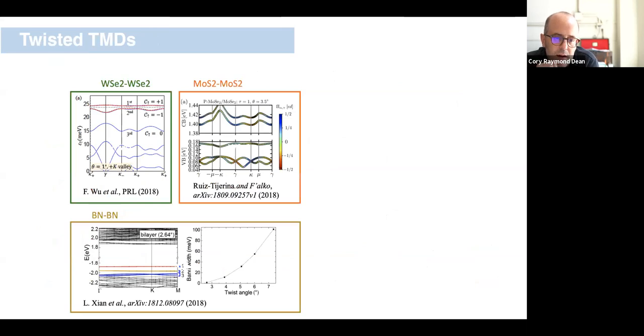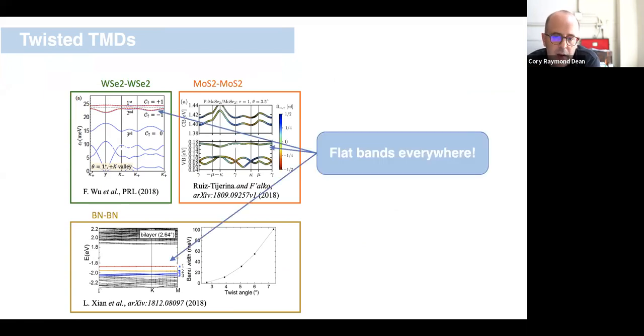And almost immediately following the publication of the twisted bilayer graphene results, several theoretical papers, I'm just highlighting a few here, pointed out that indeed you expect that you will get generically a flat band to emerge in any of the homobilayer systems, WSe2, WSe2, MoS2, MoS2, et cetera. And this also extends to heterobilayers, which I'll talk about near the end of the discussion today. Okay, so I'm just saying here, there's really flat bands everywhere.